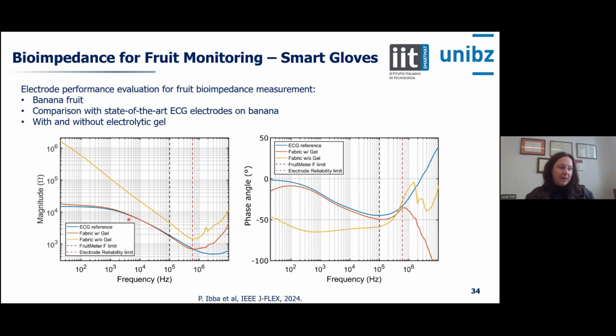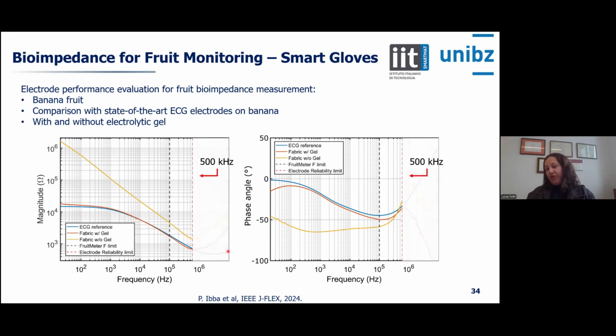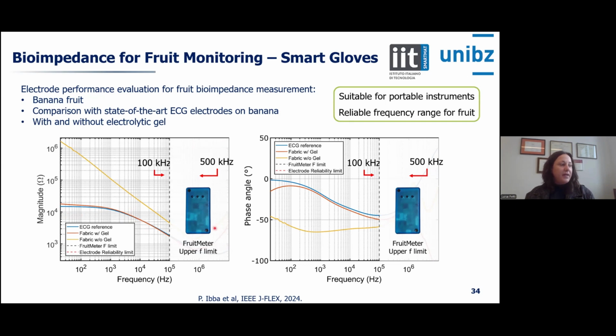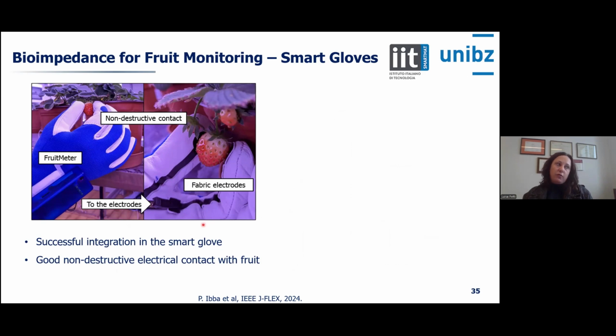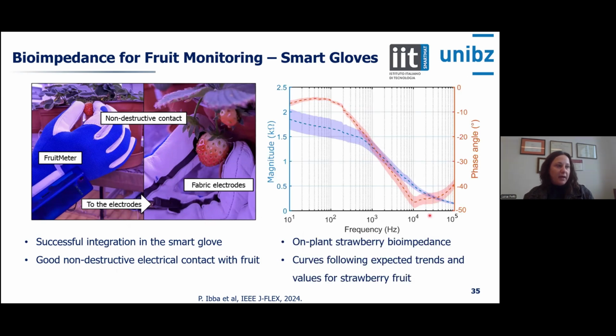So what we show is that our fabric with the gel behaves pretty good up to 500 kilohertz. But that's fine, because actually with our portable impedance analyzer, the limit is 100 kilohertz. So we can use our fabric electrodes well, but with the gel. And we also did measurements on plants for this, showing basically that we can measure. You see this integrated with the portable analyzer. We can measure on plant the impedance of strawberries, which are very tiny fruits actually, with the curve having the expected trend. So Pietro showed this recently in JFlex and the conference FETC in Bologna.